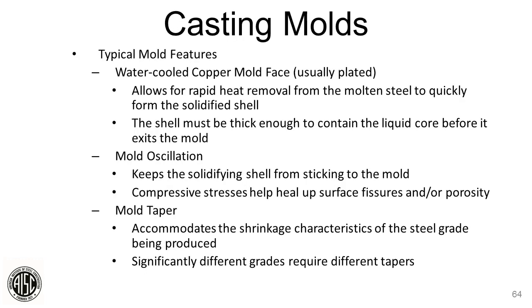It's the casting mold. The typical mold feature is a water-cooled copper mold face. It's usually plated. This allows for the rapid heat removal from the molten steel to create this solidified shell. And the shell must be thick enough to contain the liquid before it exits the mold, and that's very important. In the mold oscillation, the mold moves up and down to keep the solidifying shell from sticking to the mold. And then the taper: the mold taper has to match the shrinkage of the steel shell as it's solidifying through the caster mold. So it has a specific taper depending on the grade of steel that you're producing. And different grades of steel require different tapers. Next slide, please.